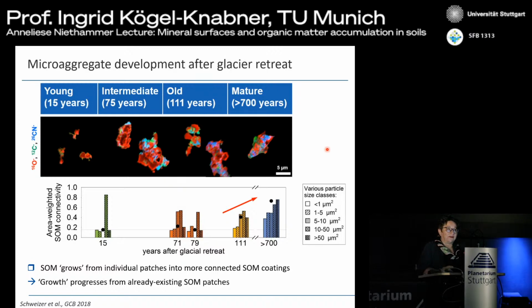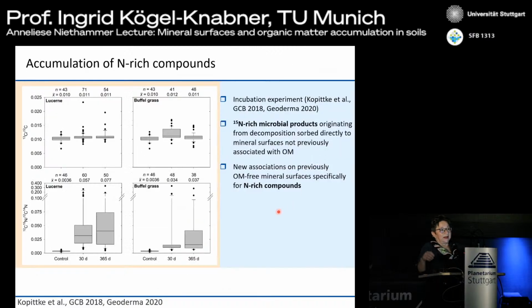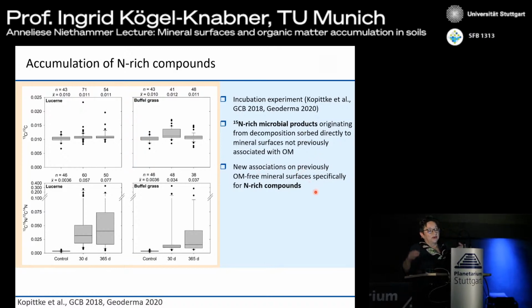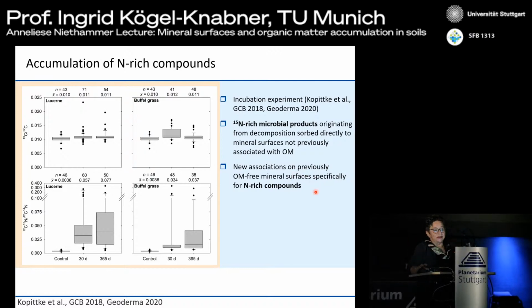So how does this growth most probably work? We think it really is a process that is associated with the growth of the microbial community in the soils. And this is an incubation experiment that Peter Kopittke from Queensland University did, and looked also at the data with us with NanoSIMS. And what we see specifically is that nitrogen-rich compounds accumulate. And we think that this is an indication that it is microbial products. And these new associations also go on beyond these spots and attach to organic matter-free mineral surfaces.